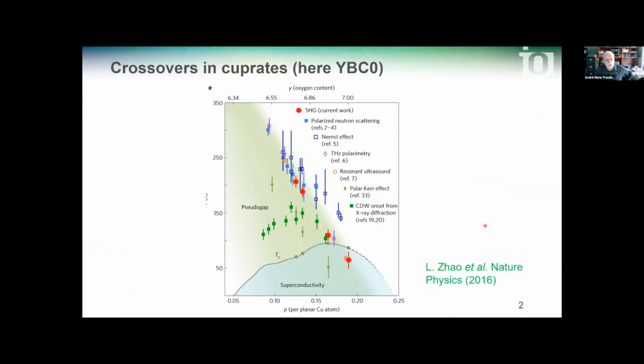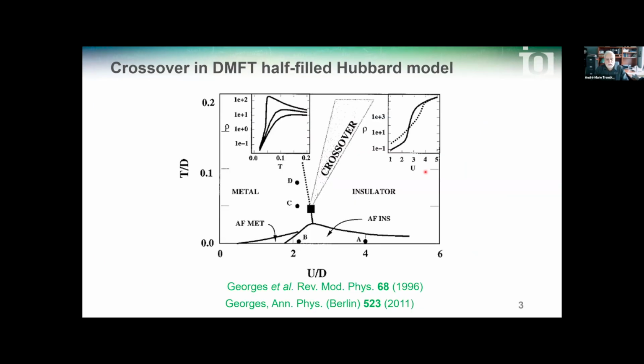In cuprates, several observable quantities exhibit crossovers to a pseudogap as temperature is decreased or doping is decreased. It's tempting to hypothesize that these crossovers tell us something about the putative critical point in the ground state. Well, dynamical mean field theory has shown a long time ago that several crossovers are observed above the critical endpoint of the Mott transition. And the importance of these crossovers has been emphasized by Antoine many times.